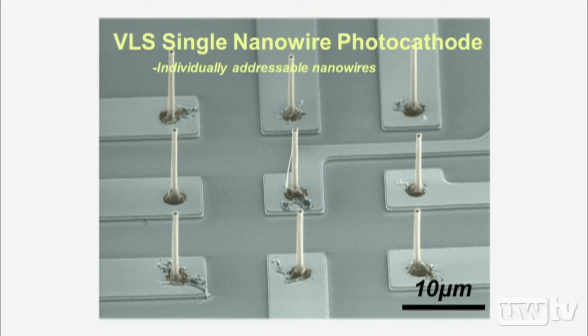And we're indeed able to measure exactly how many electrons or how many carriers we're generating from these single nanowire experiments. What you are looking at here is essentially a 3x3 individually addressable silicon nanowire photocathode. Under one sun irradiation conditions, we can measure how many electrons you are generating, and how many electrons you are sending to the silicon surface in the electrolyte.